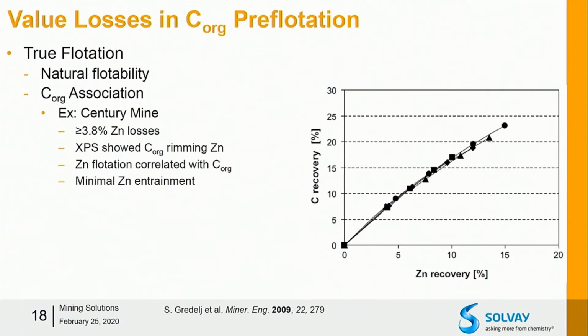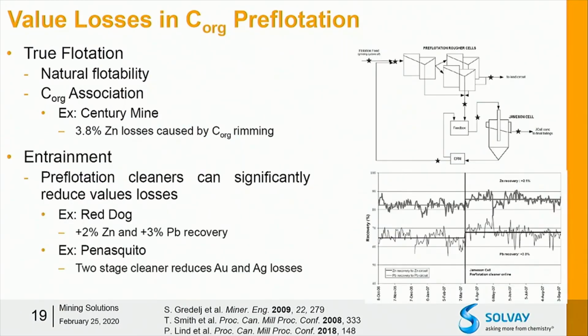However, you could also have sulfide value losses because of association. If you have this, you tend to see a linear correlation between carbon and your sulfide value across a range of different flotation operating procedures or reagent schemes. And this is actually fairly common to see. So another mechanism is entrainment, and this becomes very, very important to consider. If you're running a pre-flotation circuit, you will entrain values. It's inevitable. So one thing that I think is a must is to actually have pre-flotation cleaners.